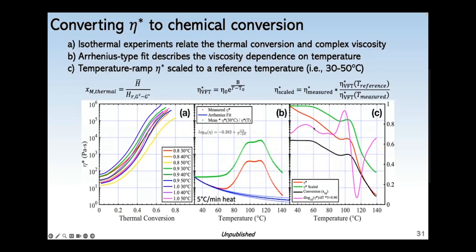And what gave me some confidence that this worked out all right is that the conversion doesn't start to decrease until about 60 C, shown in black, where I would expect the retro Diels-Alder to start becoming active for the endo adduct.